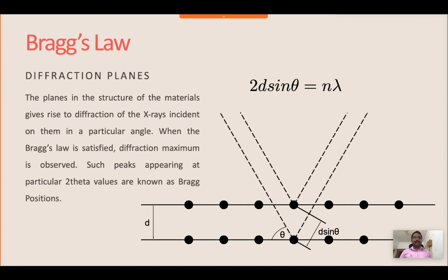So when you have a plane, I will consider two planes with a spacing of d, which is called the d spacing between two planes. Now if we have a diffraction taking place, then Bragg's law says that 2d sin theta is equal to n lambda should be satisfied. So if I take n to be 1, 2d is the d spacing between the two planes of atoms arranged in three-dimensional space. So we have theta, which is nothing but the diffraction angle.